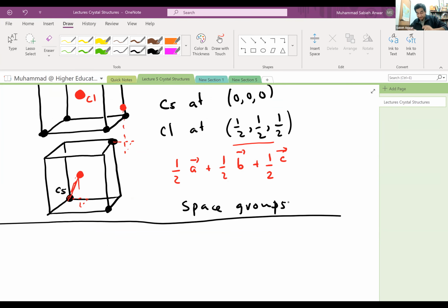By the way, if I just draw the unit cell and I put the atoms at the proper fractional coordinates inside the unit cell, and the unit cell has been drawn to its proper shape with the proper interaxial angles and the proper length ratios of the interaxial vectors, I've defined everything that I need to know about this crystal. Of course, if I forget the surfaces.